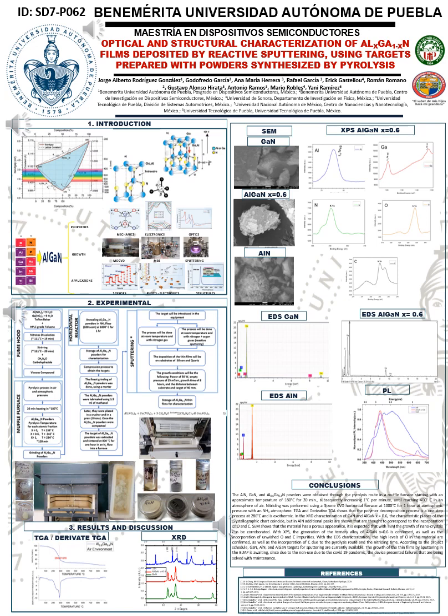Obtaining targets. The target generation process begins with the compaction of the powders into a 1-inch diameter tablet approximately 5 mm thick with an industrial press, applying a pressure of 10 tons. Sintering was carried out in a CVD furnace at 800 degrees Celsius in nitrogen flow for 1 hour, and this process was repeated until obtaining the necessary hardness to use the targets in sputtering. The targets were stored, awaiting deposition of the thin film by sputtering and reactive sputtering.